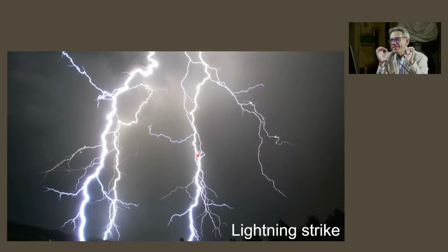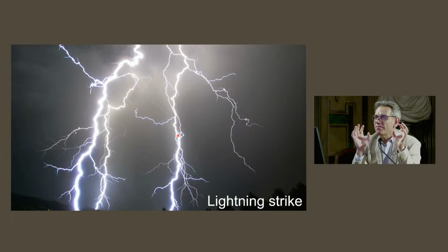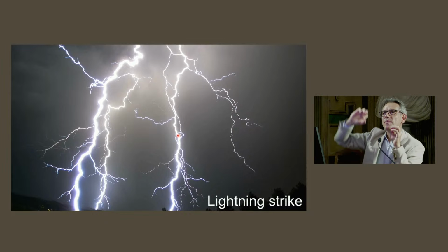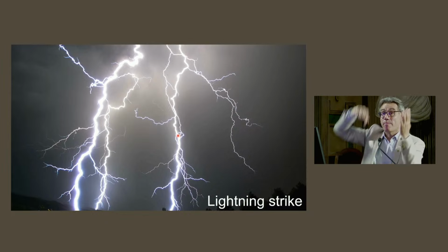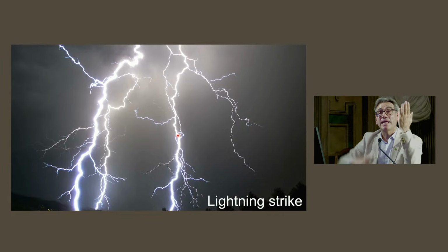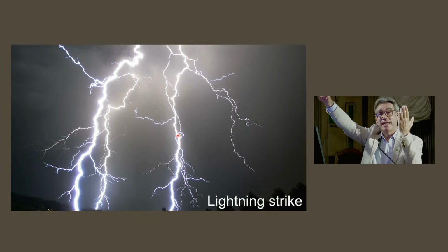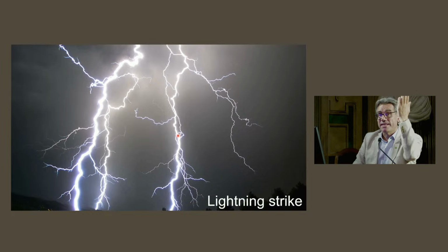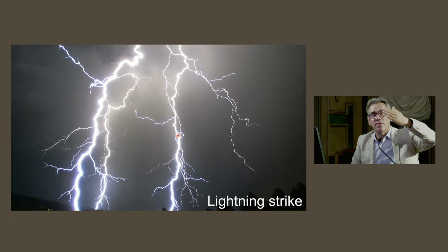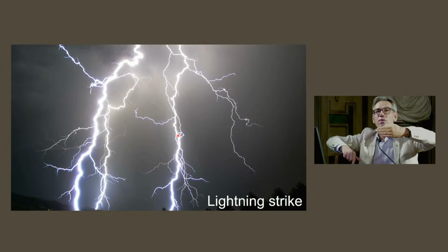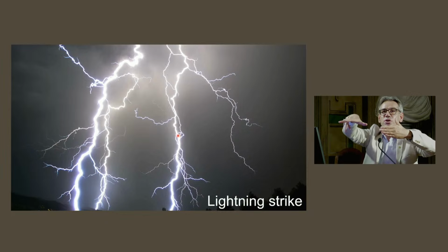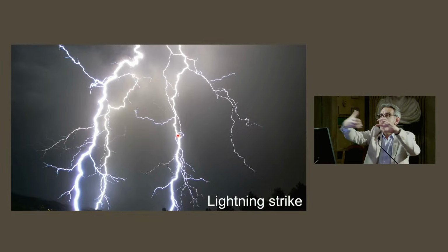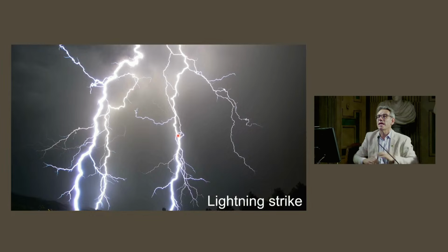Of course, I was interested in a very peculiar kind of fulgurite - one from a lightning strike hitting a power line, where there is a metal conductor. You have the melting of the metal conductor with the lightning strike, then the power line goes down, and when it arrives on the road, there is a second electrical discharge that produces the melting of the silicates on the road. You end up with the mixing of the melted metal conductor and the melted silicates, which seems very weird.